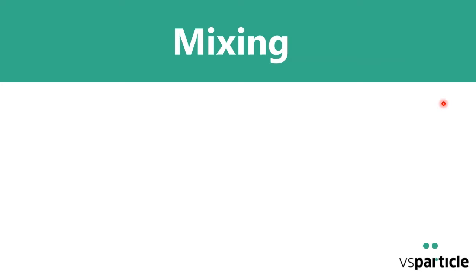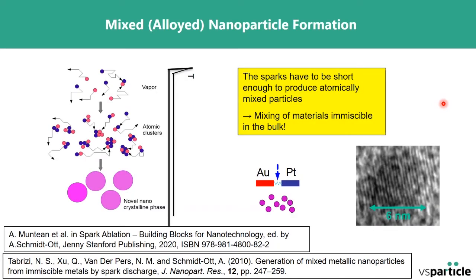Now let's come to my favorite topic, and that is mixing. If we want to make mixed particles, what we basically have to do is mix the vapors. So we make a vapor out of a material A and a material B, and what then automatically happens, if we quench as much as we do in the spark generator, is that the temperature goes down to room temperature very, very quickly. That's one of the most important features of this method. Then we get more or less instantaneous formation of atomic clusters, and they grow to form our nanoparticles of any size we want. And if, for example, we take an electrode consisting of gold and the other electrode is platinum, we will then get particles that are a mixture between gold and platinum.